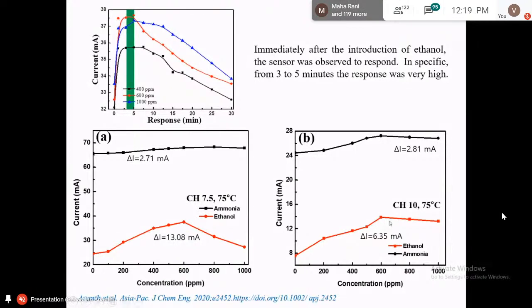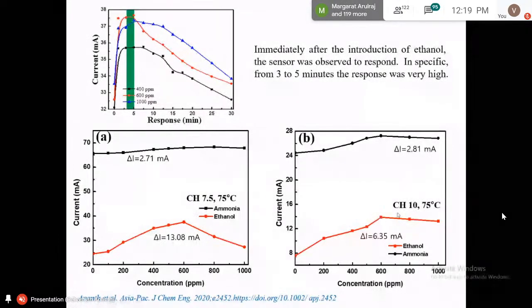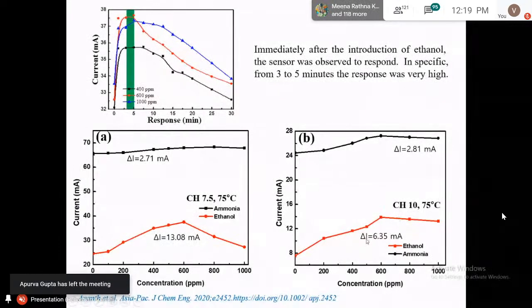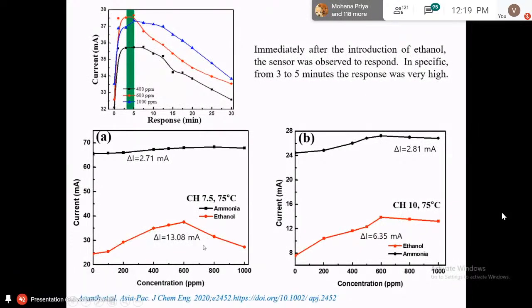Similarly, the 10 minutes cyclohexane coated sample is also showing similar behavior until 600 and then decreasing. But here the change in the current value is very small, 6.35 milliampere only. So from these two, what we can say is that the sensor should be operated at 75 degree. So this 7.5 minutes cyclohexane coating is better for ethanol sensing.